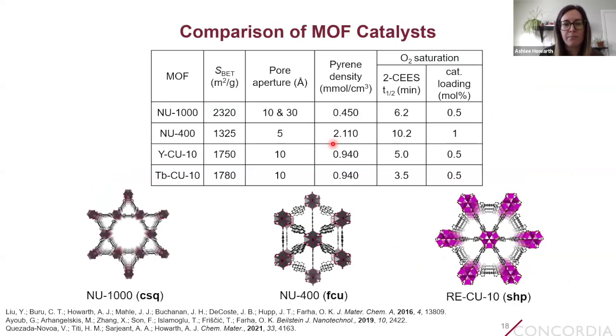So we can compare our MOF-based catalysts to some other pyrene-based MOFs that have been reported in the literature before. These are zirconium-based MOFs that also have pyrene-containing linkers. Now, what I think is most important to focus on here is the pore aperture size of the MOF, because that's important for the diffusion of reactants and products throughout the framework. And also what's important is the density of pyrene photosensitizers within the structure, because that's important for the generation of singlet oxygen.